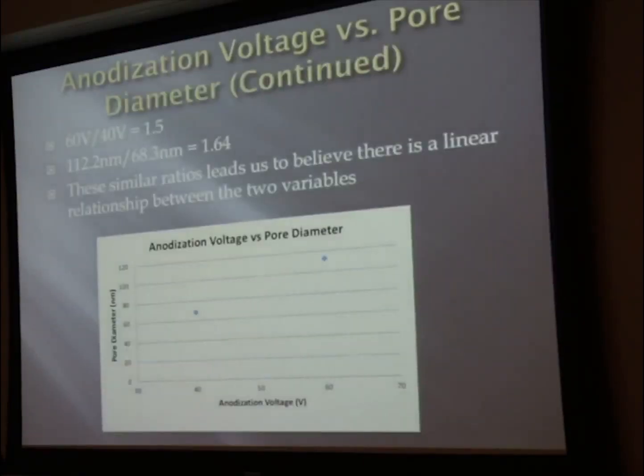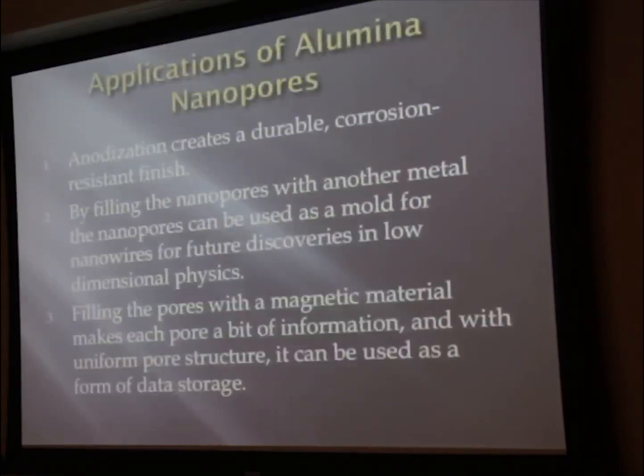And then comparing those values, the ratio of 60 to 40 volts is about 1.5, and 112 to 68 is about 1.64. So those are pretty close when you're looking at those ratios. That leads us to believe that there's probably some relationship between them, but we definitely need more data points. Currently we only have these 2 data points. Further research would be finding maybe 30 volts, 70, between 50, ranging around there, seeing if there's that linear dependence that we'd expect to see when you increase anodization voltage and diameter.